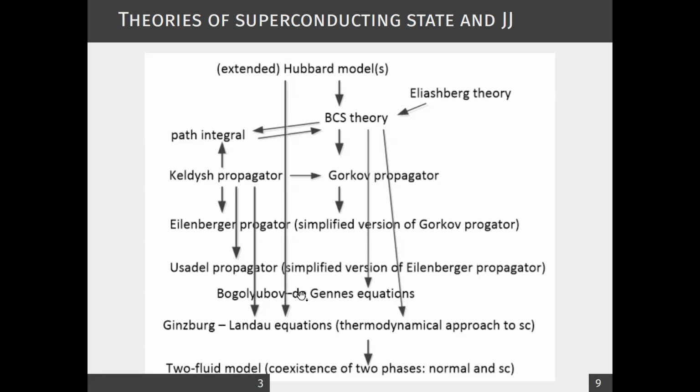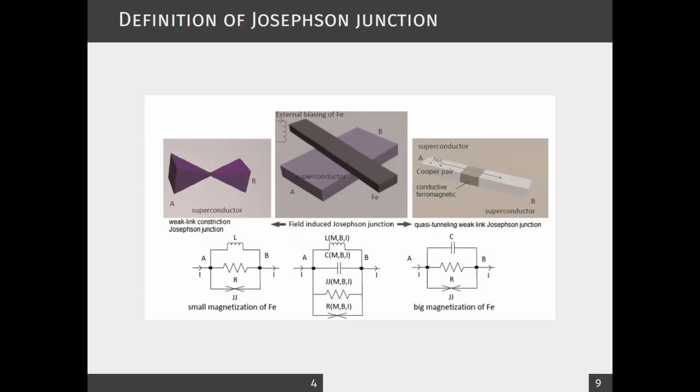All right, let me move on. I'm going to hit the simplest possible models at the very beginning. This is a picture from one of my papers in Physica Status Solidi B, 2012. I was working on a system where I have a superconducting strip, and on top of that there is a ferromagnetic strip. What happens is there is diffusion of, let's say, magnetized electrons with a certain spin orientation, normal electrons from the ferromagnet into the superconductor, and there is also diffusion of the magnetic field. The result under this strip is the induction of a quasi-normal phase, so superconductivity is destroyed.